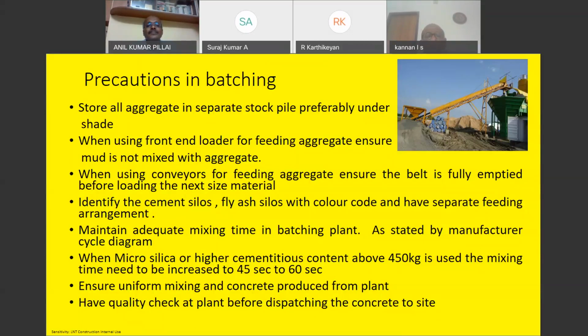When you are adding microsilica or your cementitious content is above 450 kg, you should give sufficient mixing time for the material to get mixed so that you get a uniform concrete. Normally, when you are adding microsilica or your cementitious content is more than 450 kg, the mixing time needs to be increased to 45 to 60 seconds, depending upon the content of fine or powder material added in the concrete mix design. And ensure uniform mixing of concrete produced from the plant. That is, concrete coming out of the plant should be uniform in color. Have a quality check at the plant before dispatching the concrete.